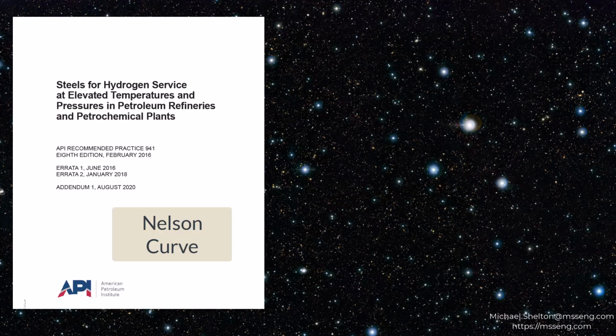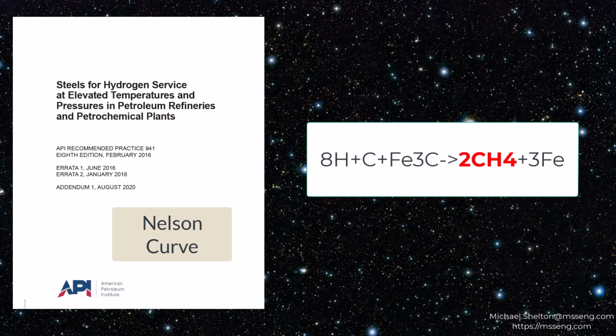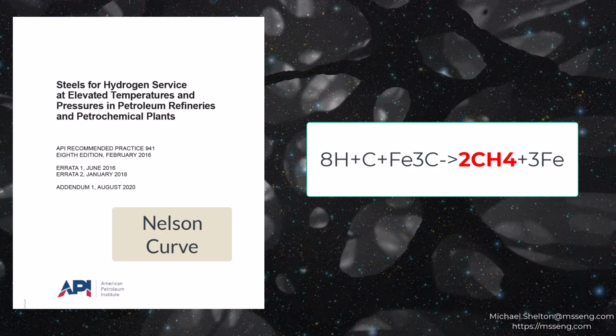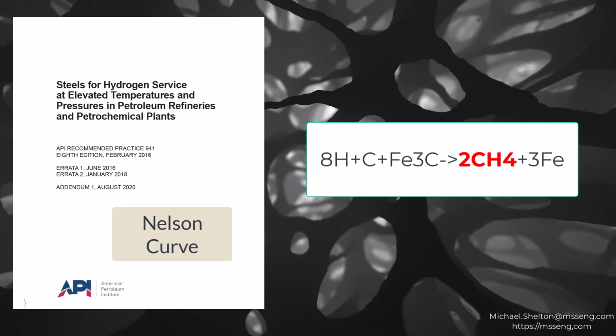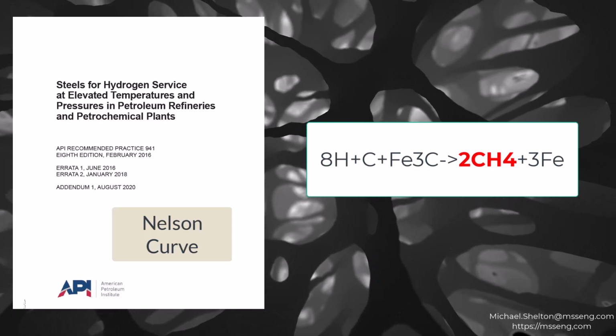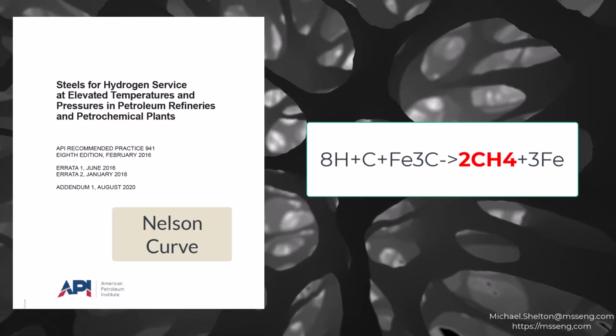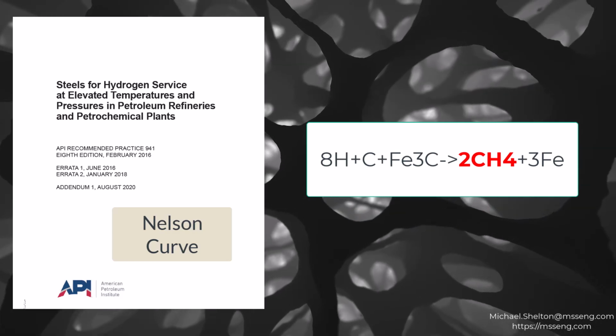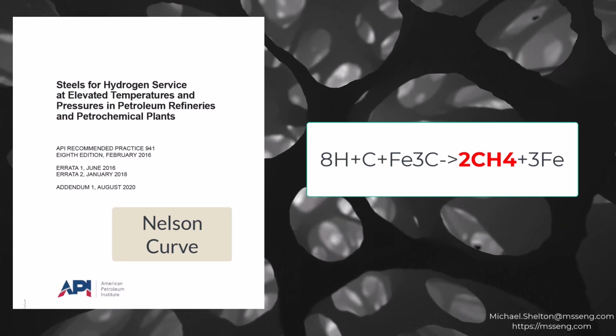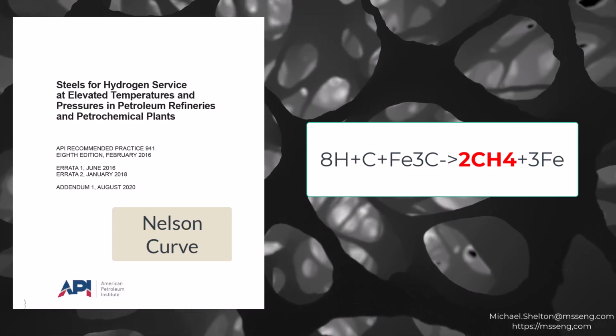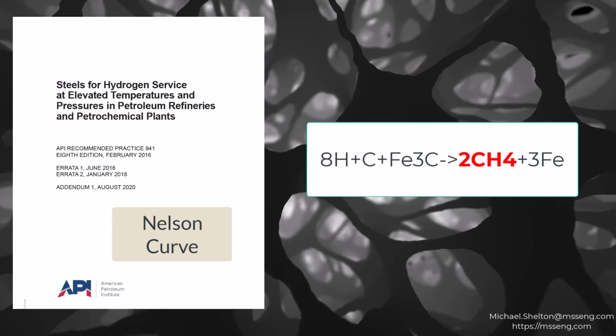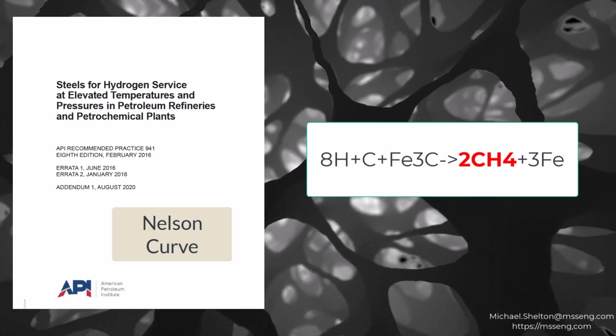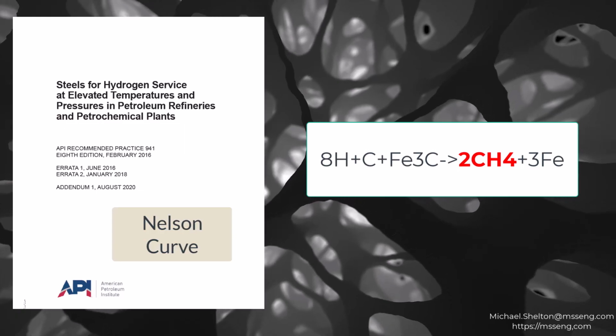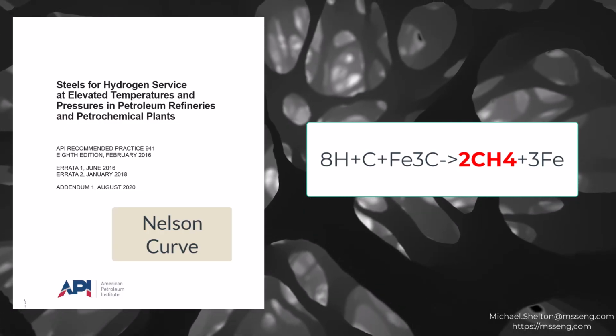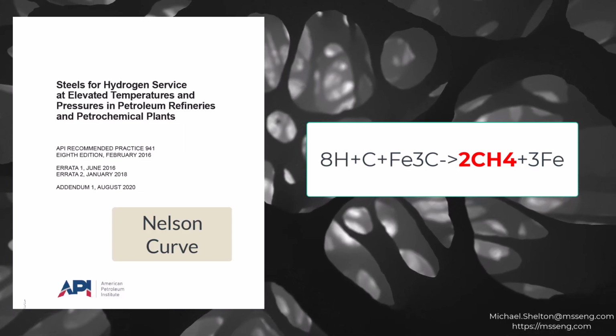Let's look at methane buildup. High temperature hydrogen attack is similar to hydrogen embrittlement, except that as ions migrate into the metal lattice, the high temperature presents the hydrogen ions trapped in the lattice with a carbon ion. It is this CH4, again, methane gas, that acts identically as the H2 gas formed with the hydrogen ions trapped in lower temperature metal lattices, both leading to hydrogen embrittlement. One is at a lower temperature and the other is at a high temperature, HTHA.